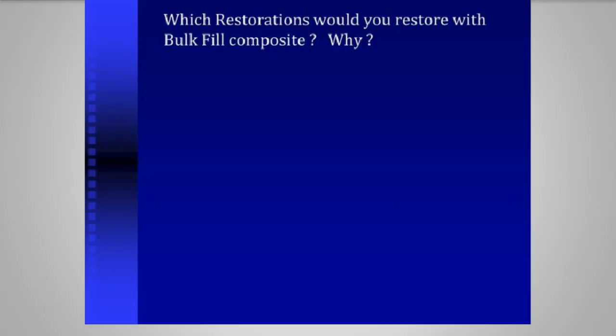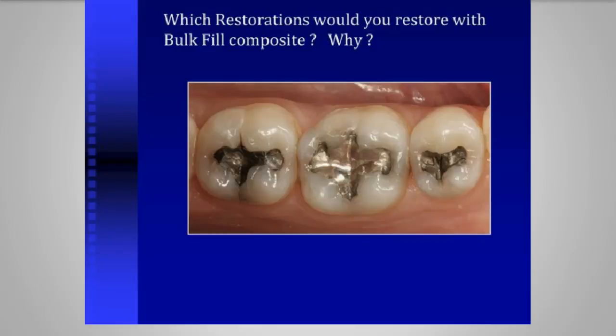Let's go through a visualization. Which restorations would you restore with bulk fill and why? I thought this was worthy to kind of stage before we get in. If we look at a typical amalgam here, and when we start looking at the surrounding cusp structures, obviously when we do a class 1 amalgam on this one, we don't need bulk curing, dual cure. It's maybe on this second molar, but we have to start thinking about what we're doing when we start creeping up into these weight-bearing areas here, and how the tooth distributes stress underneath, especially if this is hollowed out.